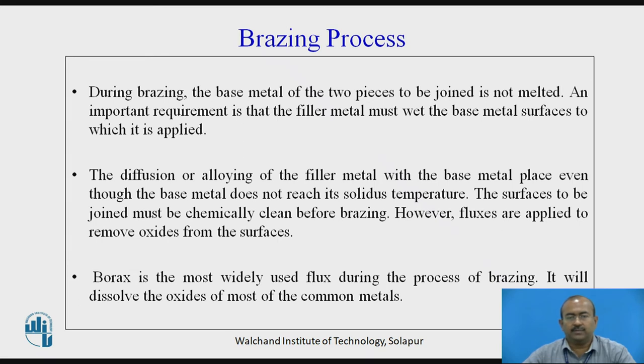During brazing, the base metal of the two pieces to be joined is not melted at all. An important requirement is that the filler metal must wet the base metal surfaces to which it is applied. Diffusion or alloying of the filler metal with the base metal takes place even though the base metal does not reach its solidus temperature. The surfaces to be joined must be chemically cleaned before brazing. Fluxes are applied to remove oxides from the surfaces. Borax is the most widely used flux during brazing; it dissolves the oxides of most common metals, thus cleaning the surfaces.